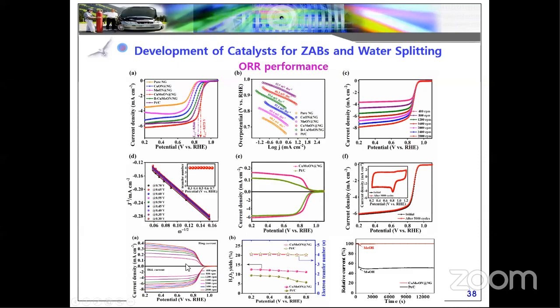And you can also run the RRDE test at different speeds. And the methanol tolerance ability is another challenge, because when we use the catalyst for fuel cell applications, methanol tolerance is very important. When we use our metal catalyst, the potential is almost retained, because there are no drops. In the case of the platinum, it drops; the relative current is reduced by almost less than 50 percent. So from the studies, our catalyst has a high methanol tolerance ability.